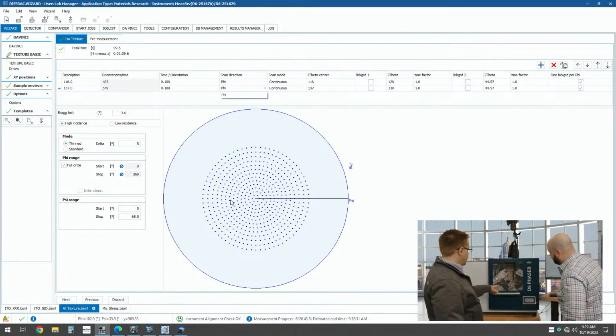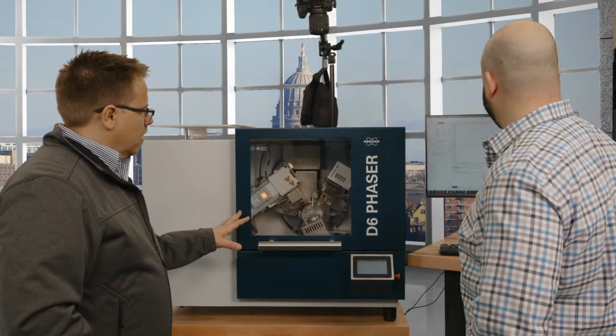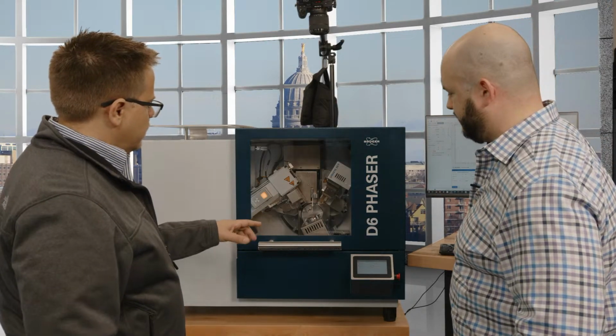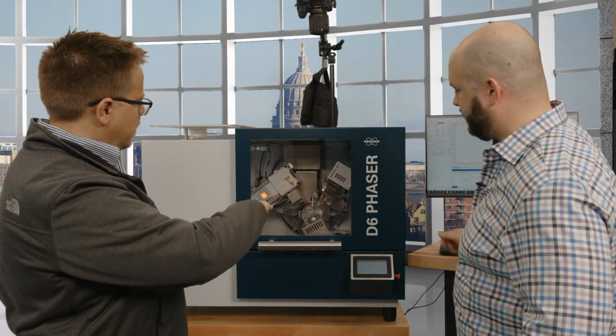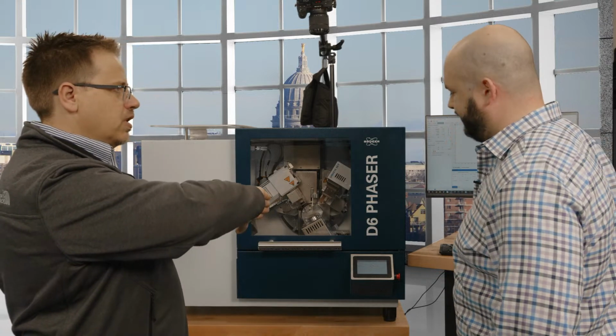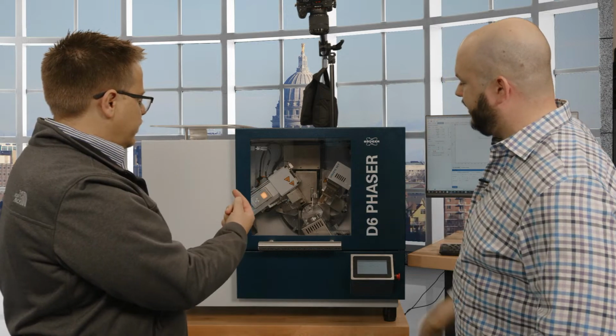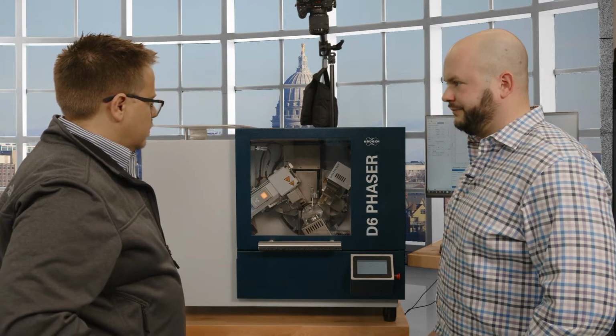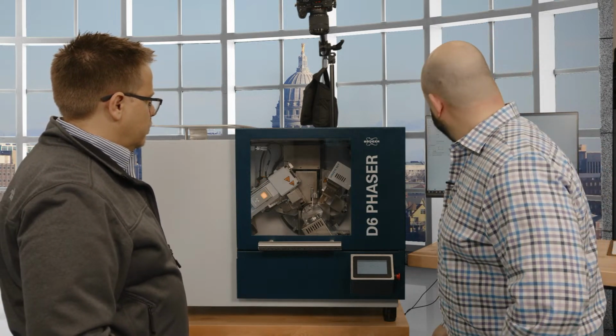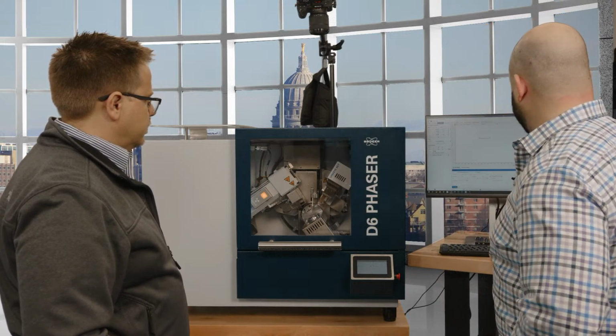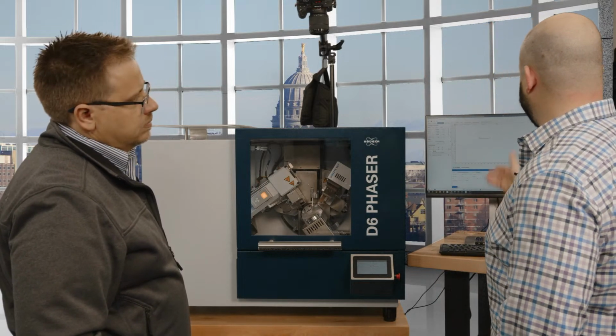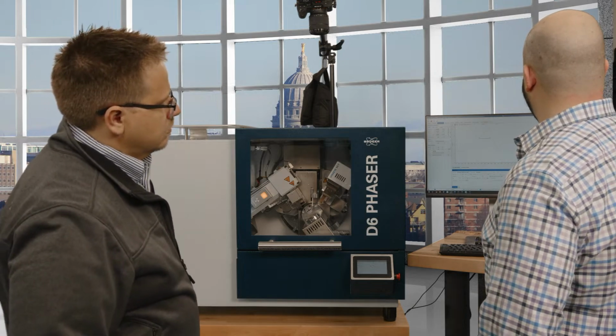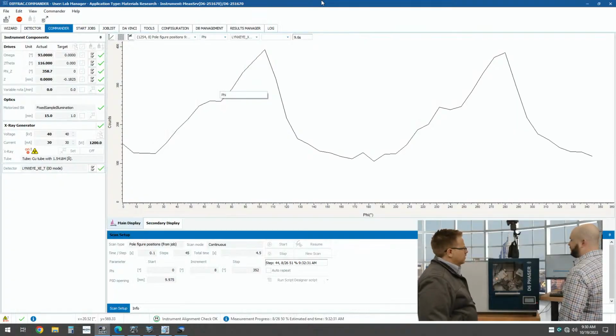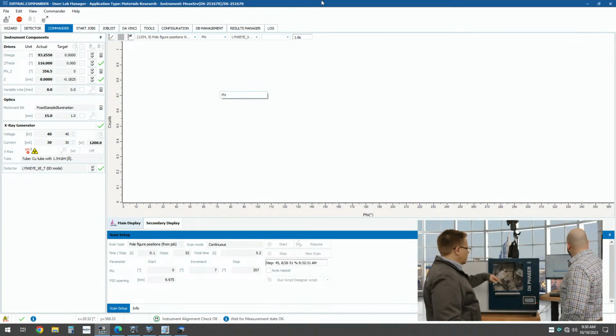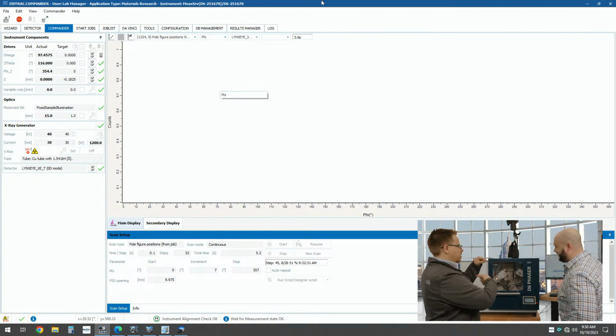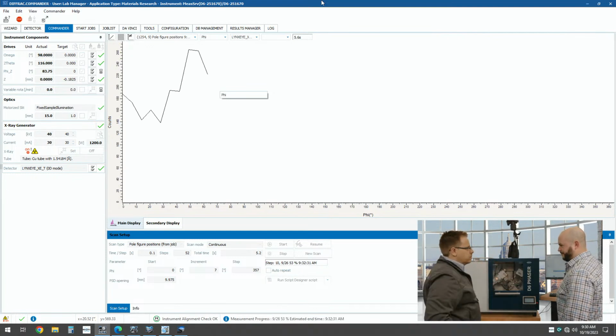So now if we look back at the machine, you can see how this measurement is progressing. It started flat, and then as it's going on, it's tilting up and up and up, and it rotates phi at each of those in order to get the data. So pretty straightforward measurement. And you can see this is the fastest texture experiment ever, and we're getting these nice peaks. So each of these is a different phi. That's a different circle on that pole figure. Yep, exactly.